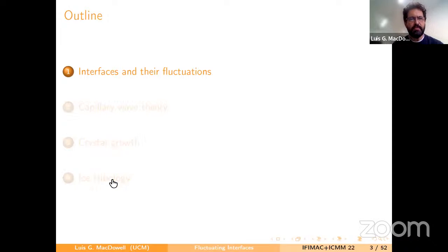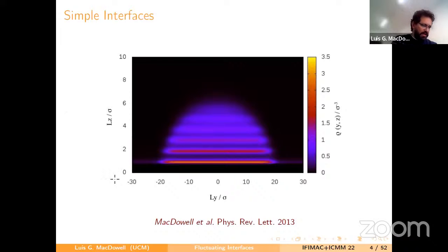So the interfaces I will be talking about initially are rather simple interfaces that are made due to the adsorption of simple atoms such as argon on ideal surfaces. Eventually, at low temperature, you can get nice structures like this droplet here. But mainly, the system is simple because the intermolecular interactions are very simple, plain hard core plus attractive tail, that we study in simulation using Lennard-Jones potentials.